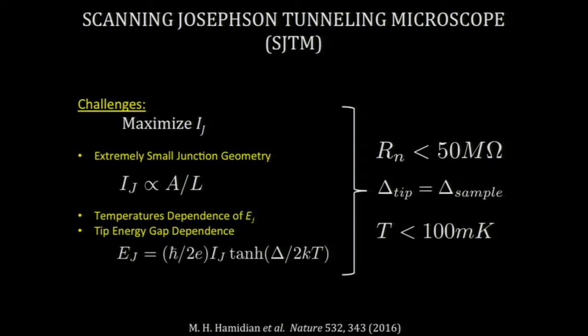And then there's also temperature dependence on how I sub J will evolve. So if you have very low temperatures, you'll have a bigger I sub J than when it's very high. And when you put it all together, the constraints end up being that this, for STM on the cuprates, is what we call a normal junction resistance. This is actually a very low junction resistance for STM on the cuprates. It means also that when you create a superconducting tip, so now you need the tip to be superconducting to make it a Josephson junction, you want that tip superconductor to be about as strong as your sample, and you've got to get to below 100 millikelvin.